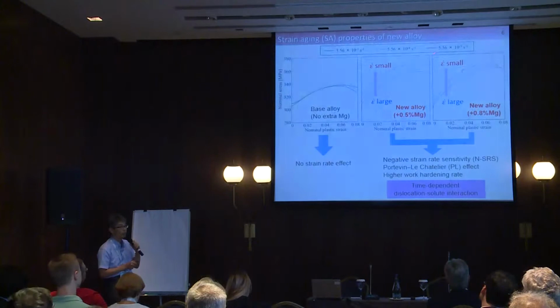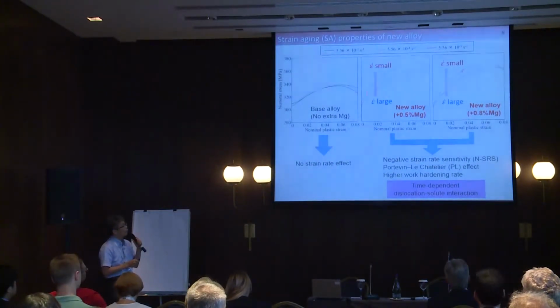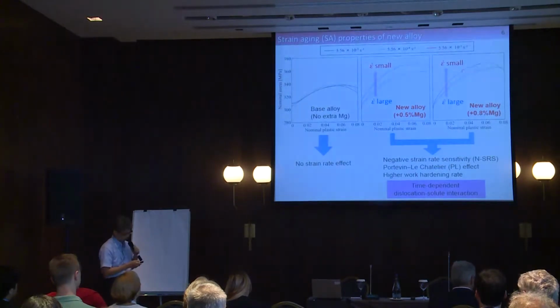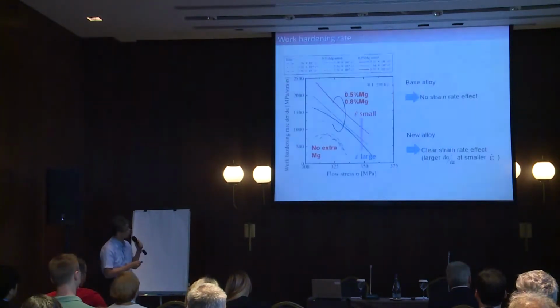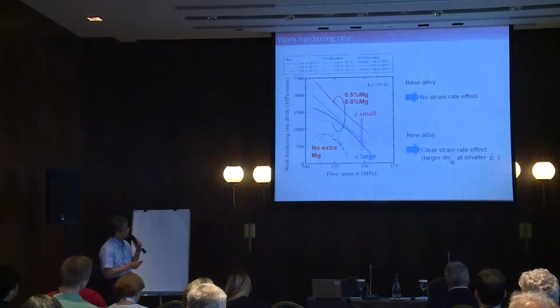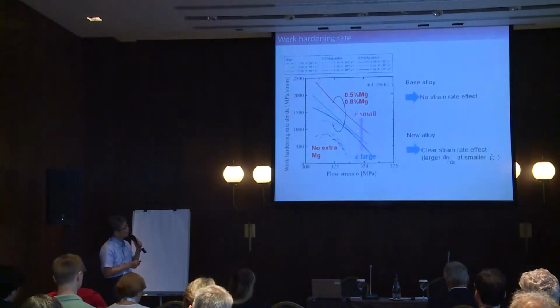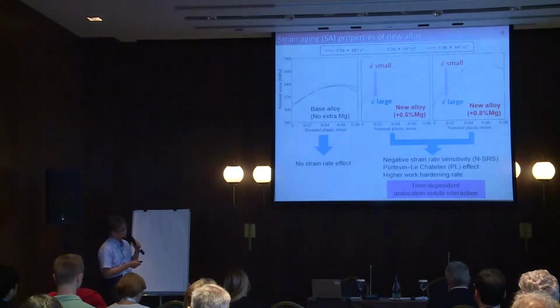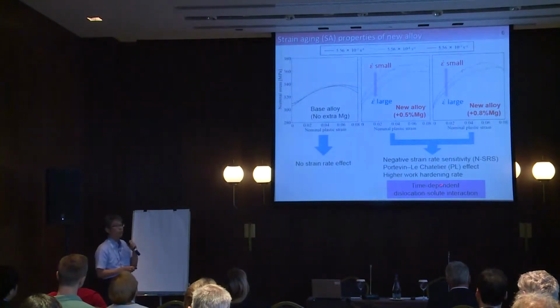Slower is stronger is very important. And also we can see vibrations or so-called serrations on the curves. And the work hardening rate is also high for the new alloy compared to the base alloy. And they clearly show the strain rate dependency. So what we can say here is that the new alloy clearly shows the time-dependent dislocation solute interaction. In other words, the strain aging property.